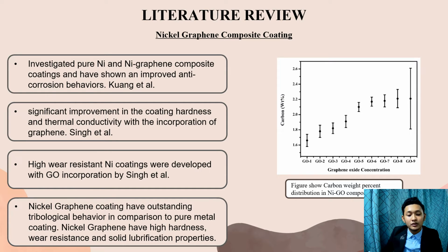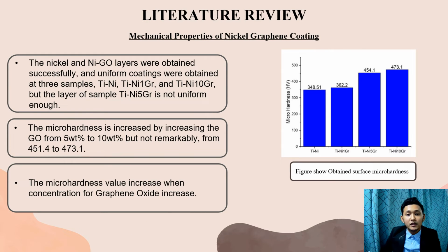Figures show carbon weight percent distribution in nickel graphene oxide composite coating. Mechanical properties of nickel graphene coating: the nickel and nickel graphene layer were obtained successfully, and uniform coating was obtained at 3 samples: titanium nickel, titanium nickel 1 graphene, and titanium nickel 10 graphene. But the layer of titanium 5 graphene is not uniform enough. The microhardness is increased by increasing the graphene oxide from 5% to 10%. The microhardness value increases when concentration of graphene oxide increases. Figure shows the obtained surface microhardness.